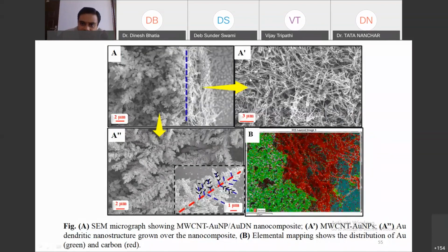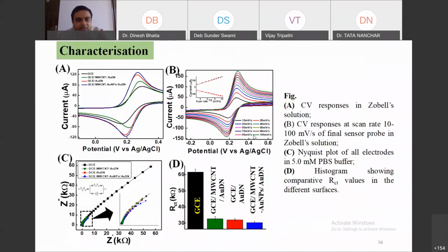You can see here the nanorods as well as the particle is very much evident, and we have zoomed in this part. This is a three-dimensional structure again, which is a tree-shaped structure. What we are discussing in all the examples, and this is again the mapping part, because this is made up of gold, actually gold three-dimensional structures, and this is made up of carbon, and this is the gold nanoparticles. So you can see the presence of all three components in the sensing matrix. So this clearly shows the presence of all three materials and the formation of a very powerful electrocatalytic material, which is a dendrite in this case.